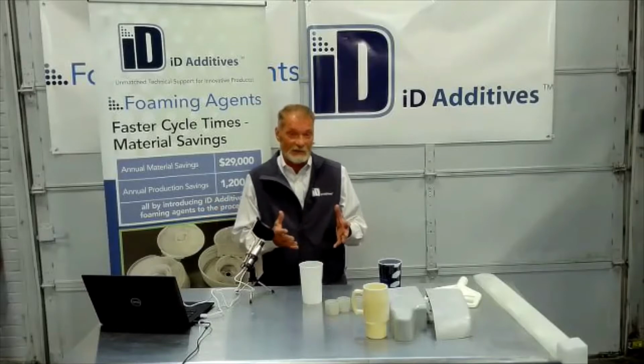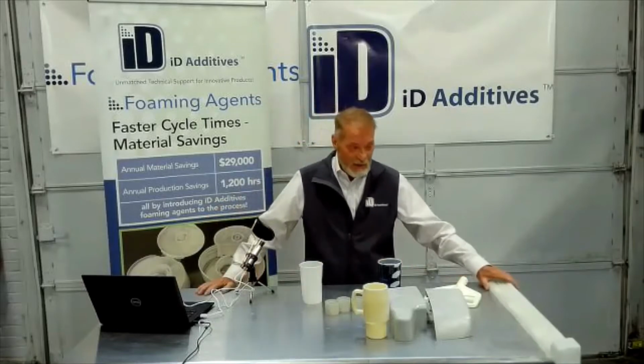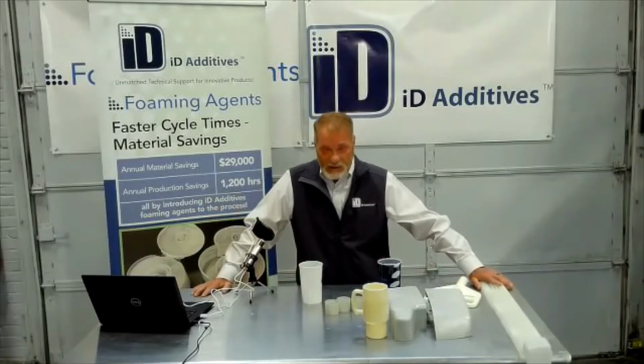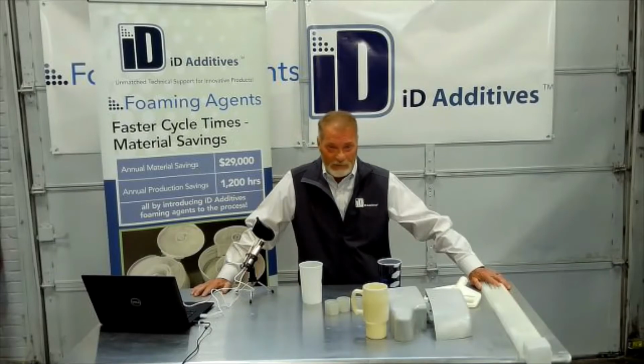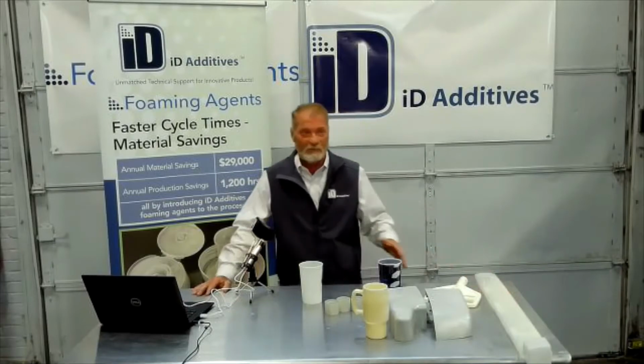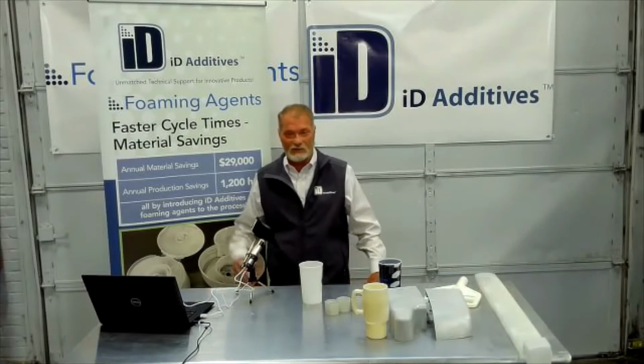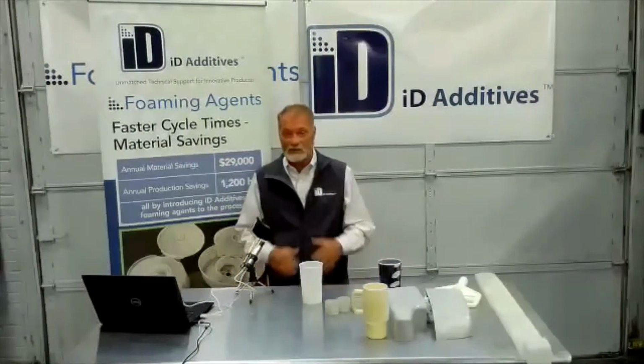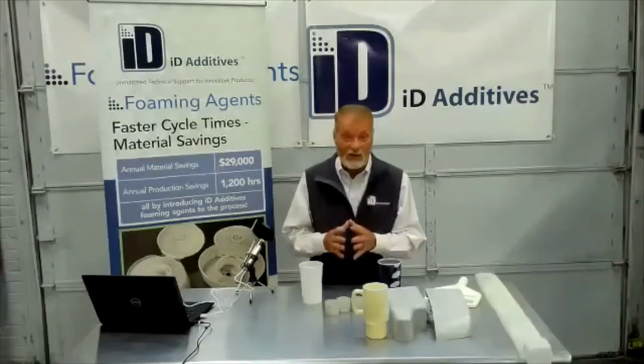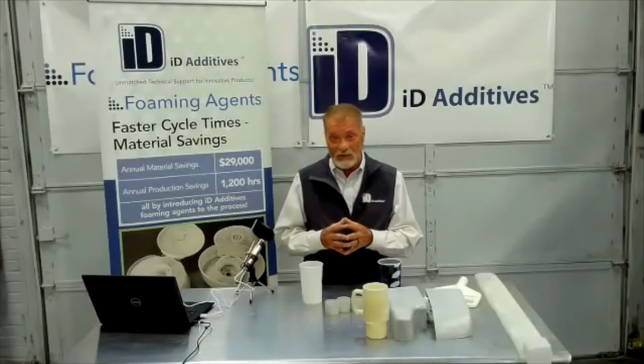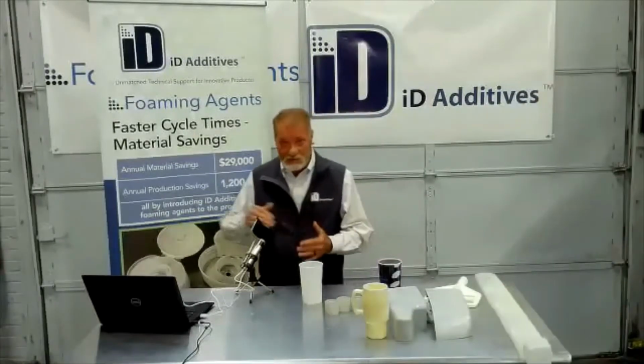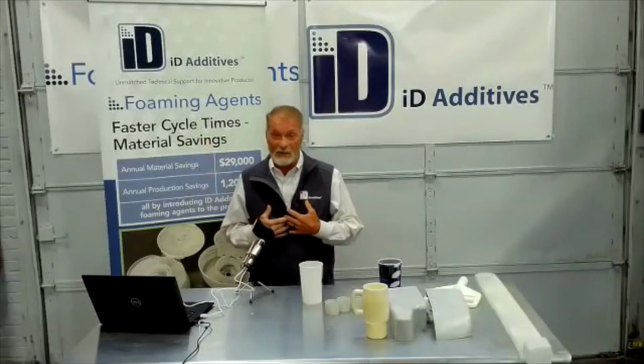I did a trial run and they had over 100 seconds delay time. We took that off and we slowed the RPM down to where it was creeping slow. But man, did it foam well. They went from a little bit of foam here and there to just a massive amount of foam just because we took the delay off. And that kind of tells you what happens to that gas. It disappears up the hopper. And believe me, you're paying for this stuff.